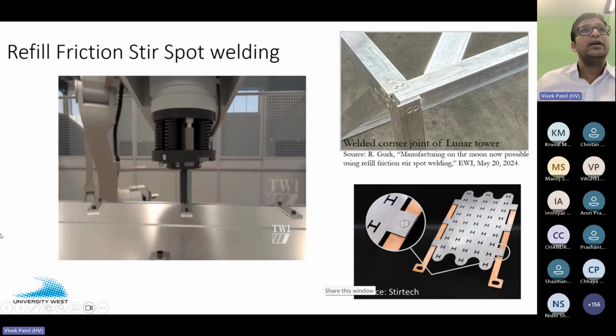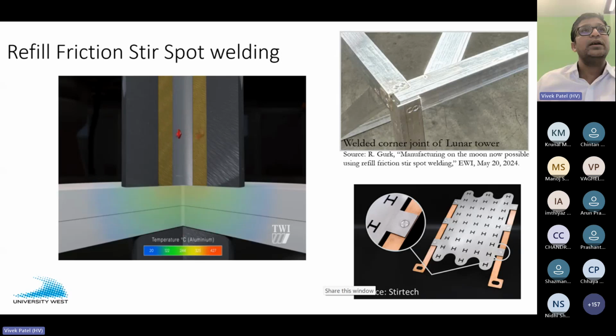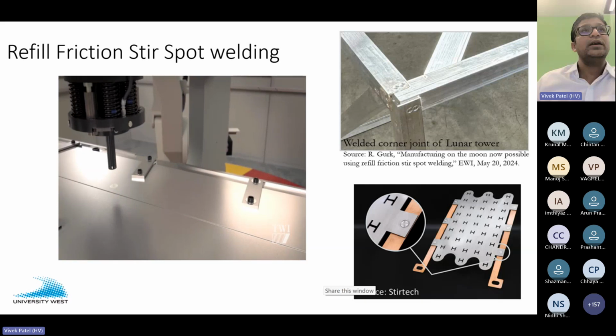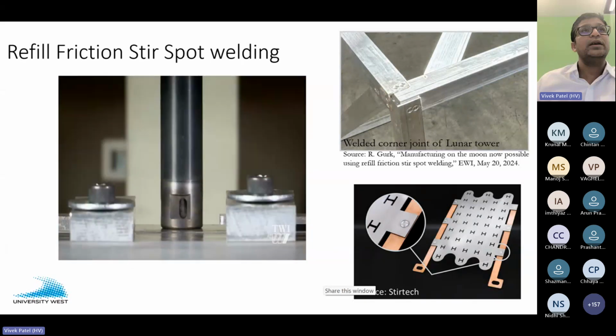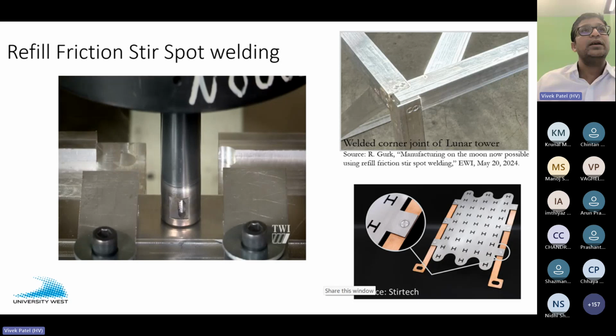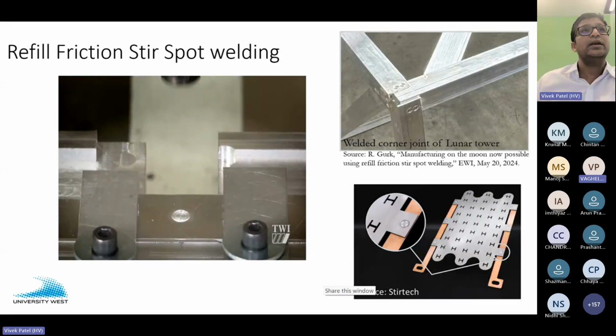You can see there is a spot welder on a robotic arm, and it has a different tooling arrangement. In this tooling arrangement, you can see that the probe is coming first, but there is another sleeve which is making the spot. And when the tool comes out, you don't have a keyhole. I would say it's a new development, and it's ideal for replacing riveted joints or resistance spot welds, and also for some applications of bimetallic joints, aluminum to copper. You can see some spots for automotive and electric connections.